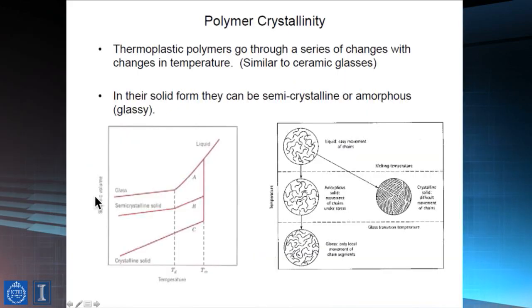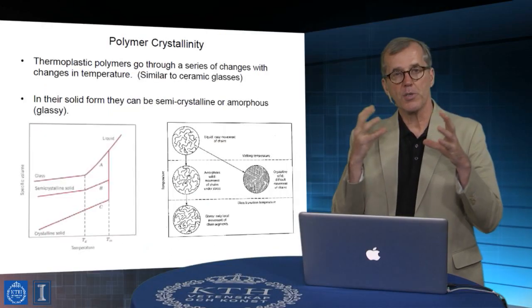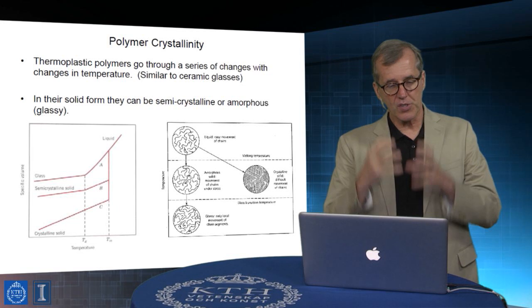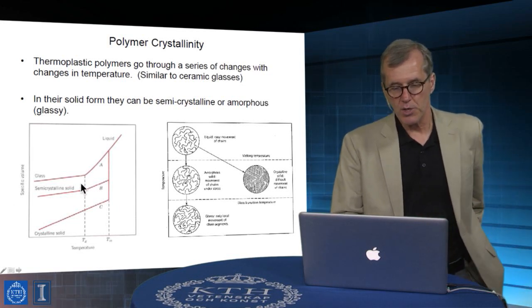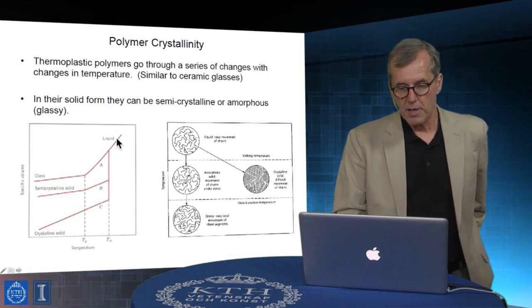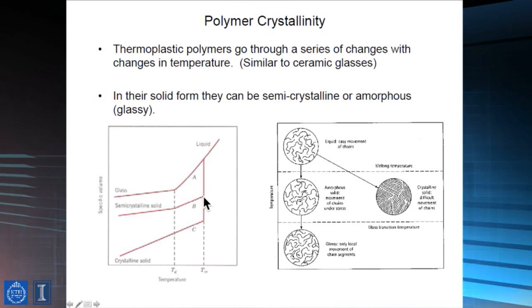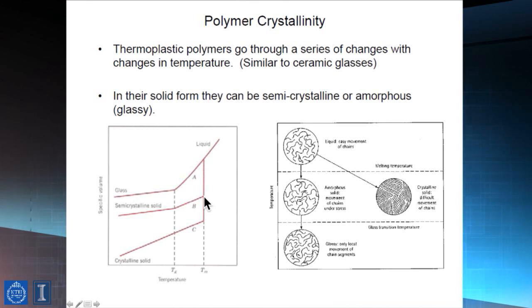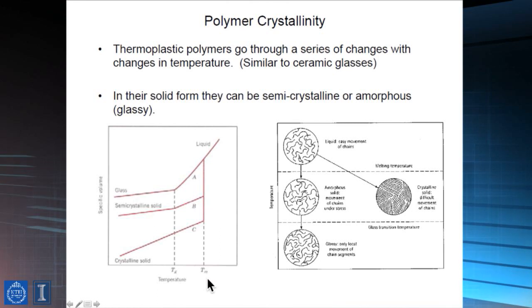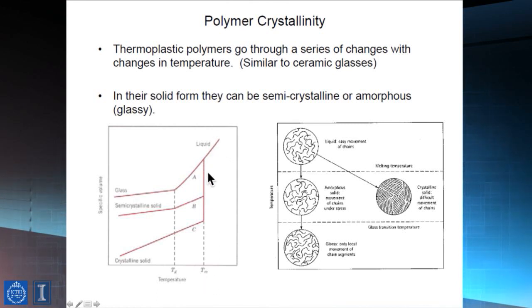So there's a plot here, plotted in terms of specific volume as a function of temperature, that illustrates what would happen during phase transitions as temperature is changed. So as a sample is cooled, right, density increases, the specific volume is going down. But if I reach a point where the cooperative motions of the components that are present there get frustrated and stuck, that's basically what we're describing as the formation of a glassy state. Or in fact, what I might see is an abrupt transition, which is shown here, along this trajectory, where there's actually a discrete phase transition, which changes specific volume discretely. That would be at the transition from the liquid to solid, right? That's the characteristic of a phase transition.